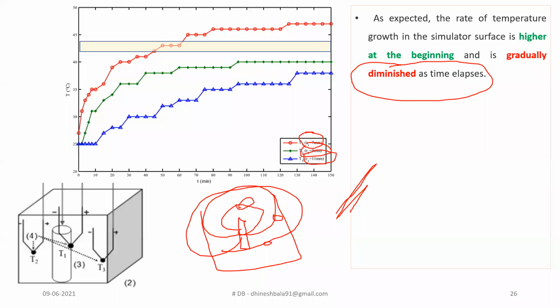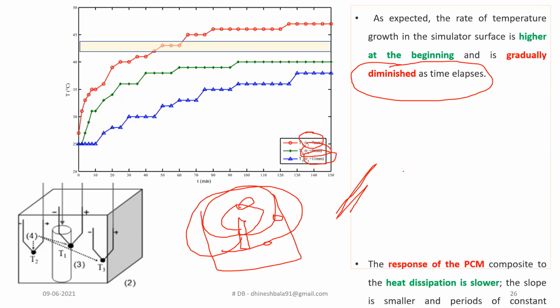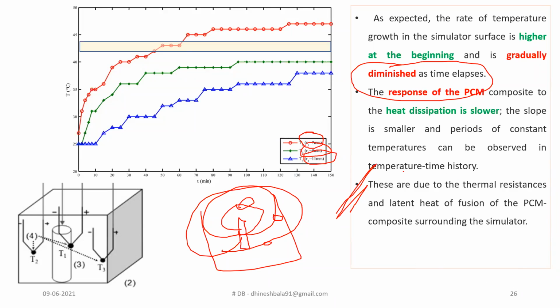But the changes would be much more evident only when the temperature reaches the melting point of the paraffin. So the melting point of the paraffin would be around 40 to 45 degrees Celsius. So till 45 degrees Celsius, you won't face any drastic temperature profile. But once you reach the temperature range of 45 degrees Celsius, you can sense there is a formation of a straight line. It means that more amount of heat is trapped in this particular zone. So the overall temperature of the system would get reduced because of this incorporation of phase change material closer to the battery.